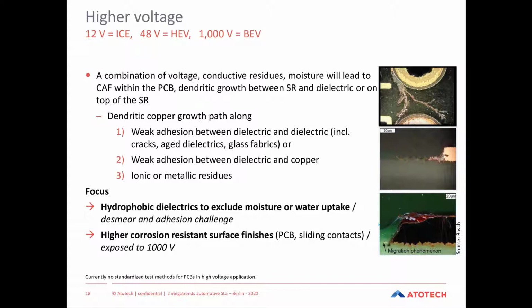This will result, on the other hand, in issues like CAF, conductive anodic filaments. And this especially when moisture and ionic contamination are present. Dendritic copper growth between the solder resist and the dielectric will occur. This will at the end create shorts.